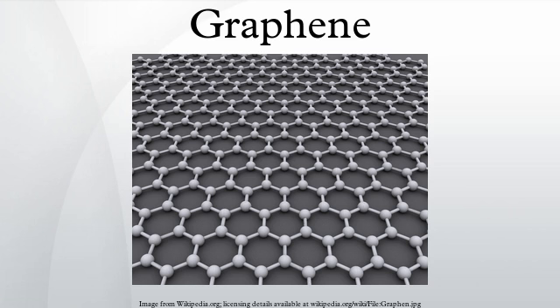Refluxing single-layer graphene oxide in solvents leads to size reduction and folding of individual sheets as well as loss of carboxylic group functionality, by up to 20%, indicating thermal instabilities of SLGO sheets dependent on their preparation methodology. When using thionyl chloride, acyl chloride groups result, which can then form aliphatic and aromatic amides with a reactivity conversion of around 70–80%. Hydrazine reflux is commonly used for reducing SLGO to SLG(R), but titrations show that only around 20–30% of the carboxylic groups are lost, leaving a significant number available for chemical attachment.